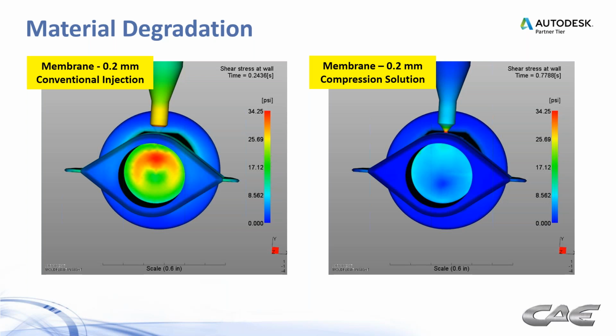So this molded in stress can actually reduce the amount of yield stress required to make a part fail in its functionality. So notice the difference here between the conventional injection and the compression solution. So there's, on the same scale, quite a reduction in the amount of molded in stress in that part.